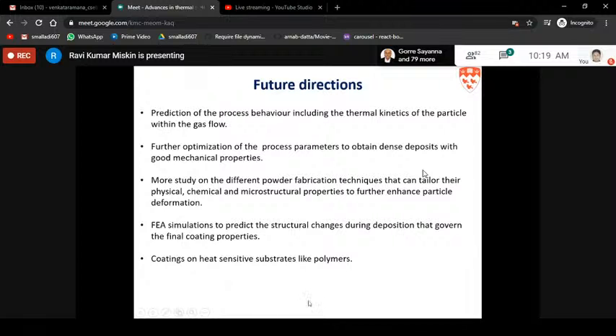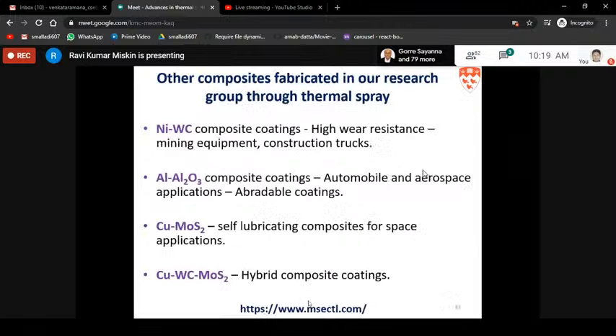So some coatings which were studied by my colleagues include nickel tungsten carbide composite coating. It's for high wear resistance applications: mining equipment, construction trucks, that's drilling and digging equipment. We have some alumina composite coating we studied that was mostly for aerospace and automobile applications. There was also copper MoS2, copper molybdenum disulfide.